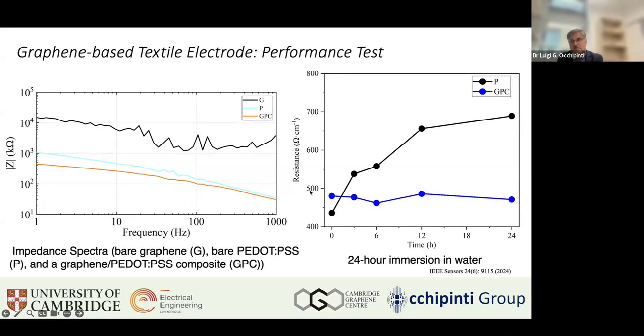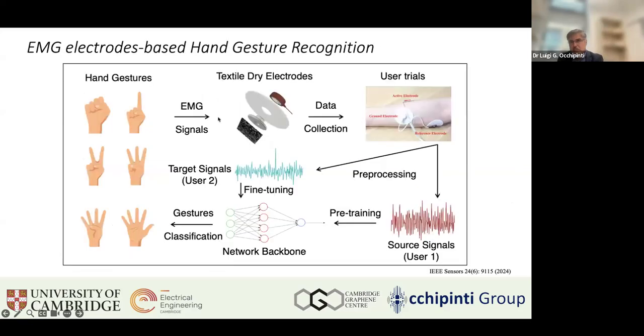Not only that, but also in terms of stability, as you can see, the PEDOT:PSS tends to have a slight degradation over time when immersed in water, while the graphene PEDOT:PSS coated electrode maintains its stability over time. We believe that the graphene acts as a protective material. And we proved the effectiveness of this dry electrode in a simple experiment for hand gesture recognition. The standard configuration of the 3 electrodes in the forearm was used to collect the data. We also used transfer learning to optimize the training process and tested over 2 different users.